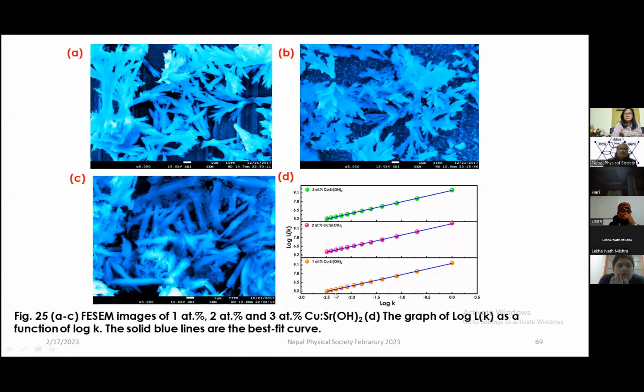So what we have done, we have discretized it and obtained that value, put it there. Then we have plotted this curve. If this curve, log Lk versus log K, is a straight line, then this shows that it has the fractal character. Otherwise, it does not have the fractal character. So this shows that copper doped strontium hydroxide is showing the fractal behavior.